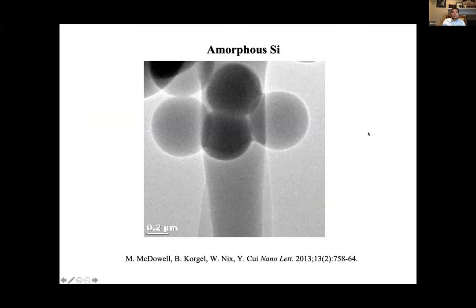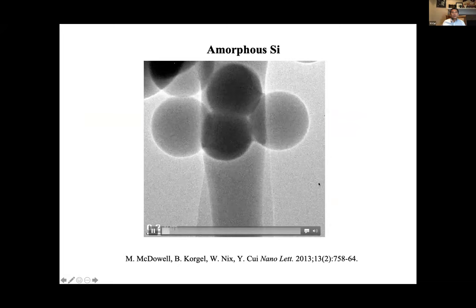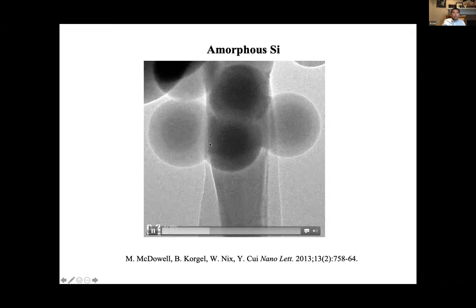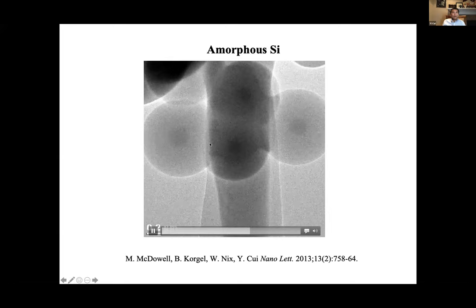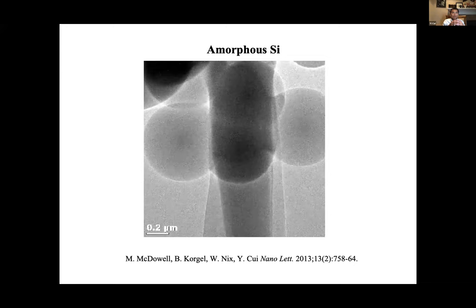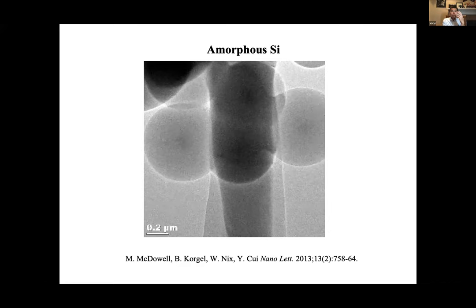I also want to share the rich phenomena at the materials level. If you use amorphous silicon particles to start with, the behavior is completely different. Amorphous silicon has many dangling bonds and a lower density — there are point defects and vacancies. When you put lithium in, it is more tolerant of the volume expansion because the stress level building up is not as large. Big particles, up to a micron in size, can survive the volume expansion.